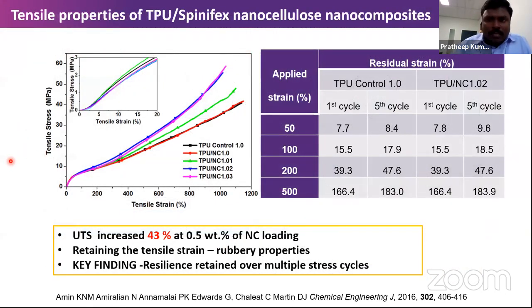tensile strength. For elastomers, the tensile strength improvement is really important. So she could improve up to 43% of the tensile strength, within 0.5 weight percentage loading of the nanocellulose. And this particular type of nanocellulose actually provides the resiliency. What it means is, when you are doing multiple cycles of stretching and releasing, your material should not become stiffer, and it should not become softer as well. So it needs to maintain its elasticity and resilient properties.